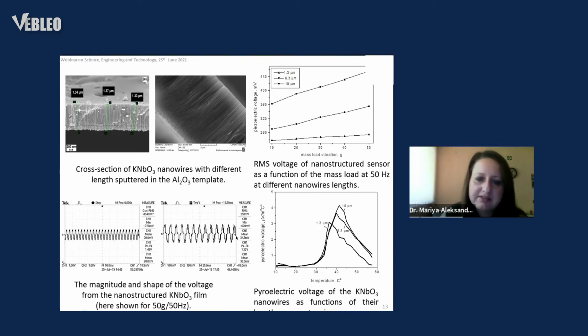If we compare the signals, again, there are some distortions. Of course, it is expected because on the top, the contacting electrode could realize only the point-to-point contact, not so regular and uniform like for the dense coating, but the distortions are less than 10%, so it could be easily filtered with the proper electronics.